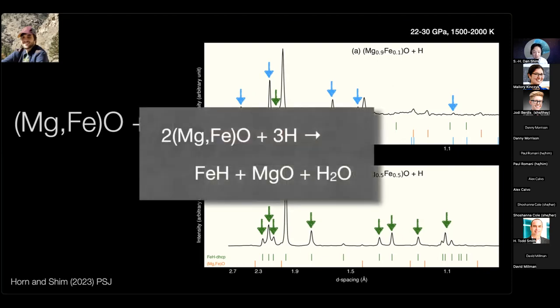In fact, if you write out these observations and chemically balance the before and after chemical reactions, you'll find that the hydrogen and MgFeO reaction produces an iron-hydrogen alloy, with MgO left as an oxide. And because you reduce the iron 2+ into iron metal, that allows some amount of oxygen to be released to the hydrogen atmosphere that ultimately reacts with hydrogen and forms water. So the water formation is a natural consequence of this chemical reaction.